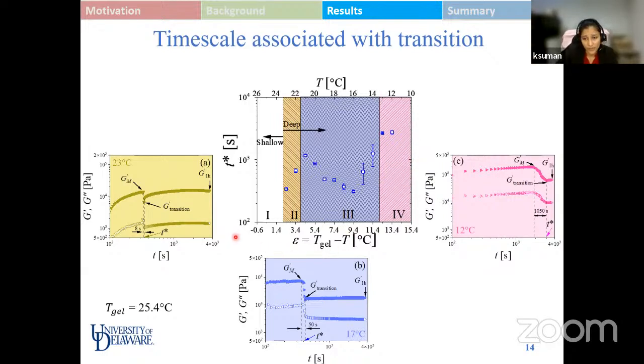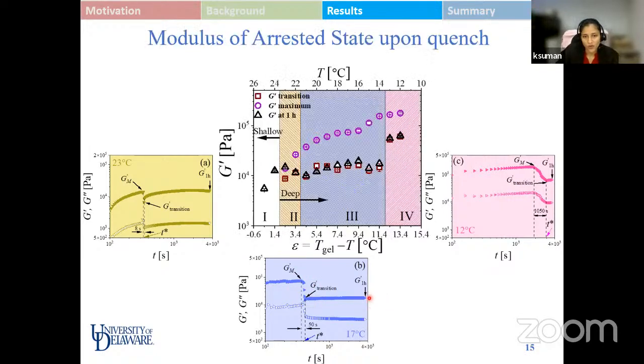Also important parameters in all these figures is the value of modulus, which is at the maximum value at the point of transition and at the end of 1 hour of aging study. So we now plot the value of modulus at 3 different stages during the aging study, which is the maximum value, the transition value, and at the end of 1 hour experiment. As we can see, with increase in the depth of quenching, the value of modulus increases.